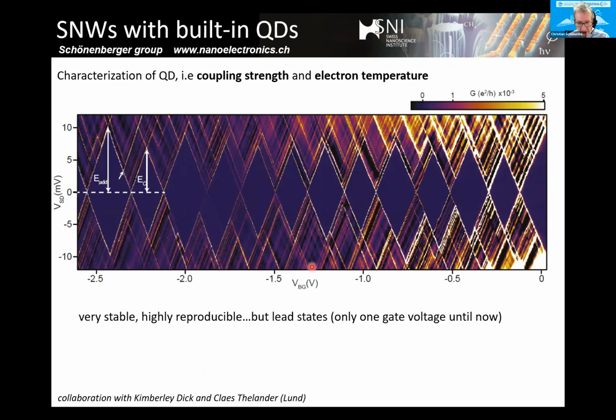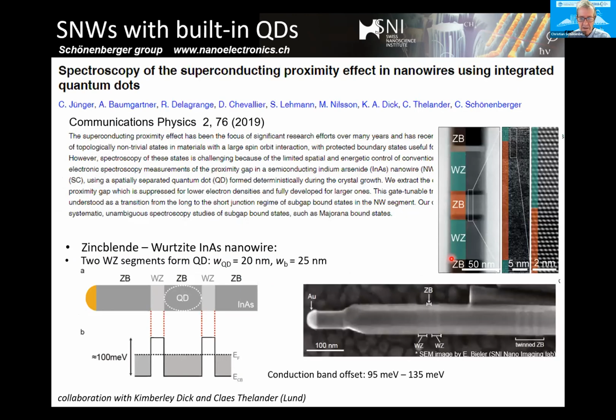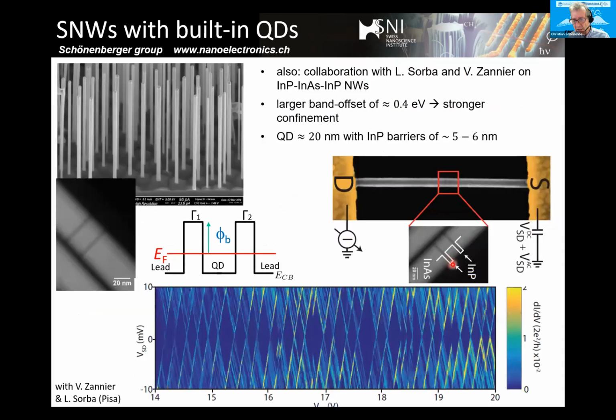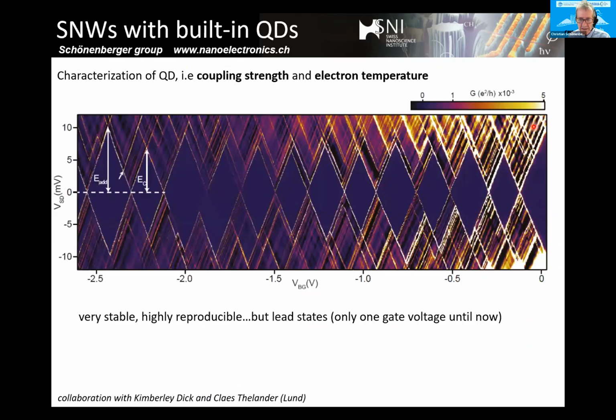And you see many lines here outside the Coulomb blockade region, and most of these are not the excitations of the dot. They're actually structures from the lead. So maybe this picture here, when you think you have the quantum dot here, we connect it with some long leads, maybe a few hundred nanometer long, and then there are bound states. You know, if the crystals are very good, then you have ballistic transport here, and then bound states form. We call them lead states, and all these lead states you see as spectral features in these measurements.